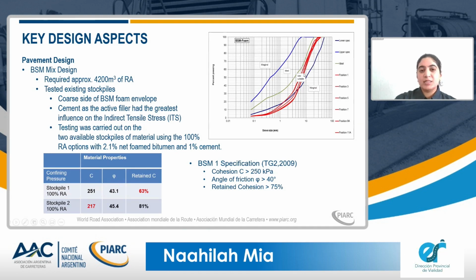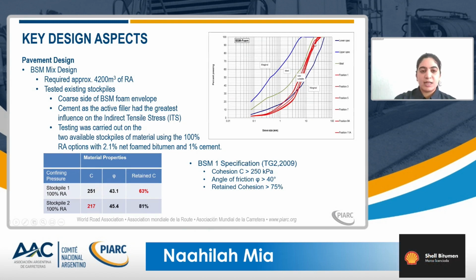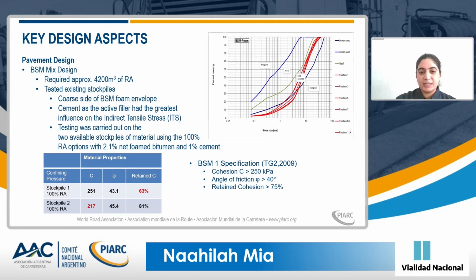The testing of the RA stockpiles that we did formed part of the coarser side of the BSM foam envelope. So you can see from the picture on the right-hand side that the grading of the material was more on the coarser side. Cement and lime were the 2 options for an active filler. However, after we had done some tests, we realized that the cement would be used as the active filler as it had a greater influence on the indirect tensile stress test.